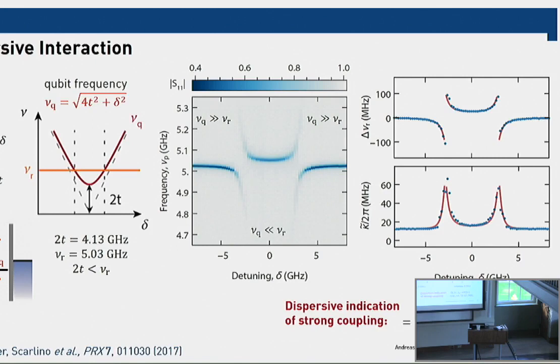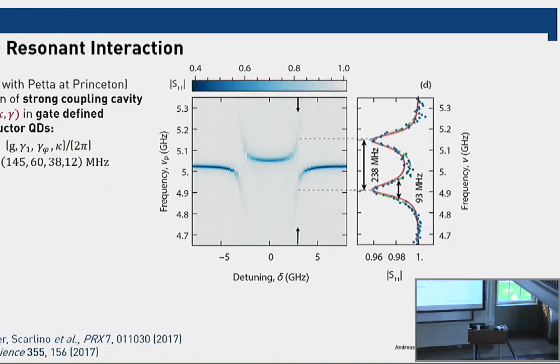And you see it both from the line width of the resonator and also from the frequency shift of the resonator. But then you would like to go into resonance and see whether you can actually observe a vacuum Rabi mode splitting. And lo and behold, you see that we could observe a vacuum Rabi mode splitting for charges in this semiconductor double quantum dot.